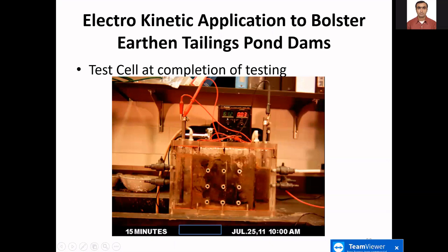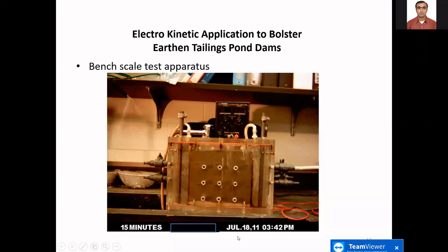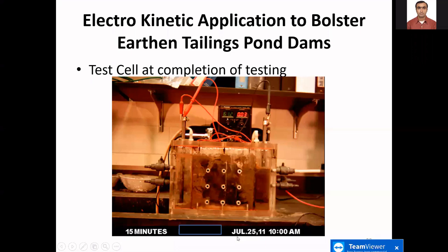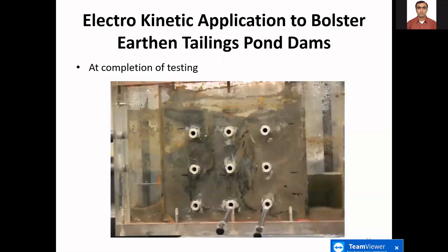Okay, so that was done on July 18th, 2011. Seven days later, which is actually a good determination, because we were finding that it only required approximately 6 to 7 days on most samples that we treated, 6 to 7 days of application of power to get sufficient treatment to mold the clay, the slimy material, and express the necessary water, getting the water content down into the lower 60% range.